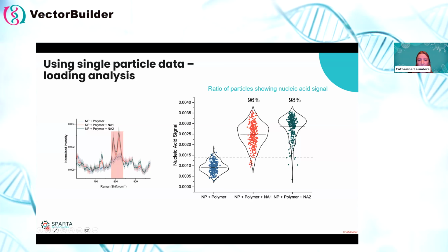So I should say this was a very short type of RNA that was used here. So we're expecting there to be tens to hundreds with a reasonable distribution of particles, rather than the more discrete, empty, full populations you might expect from the longer RNAs. So this is showing us the ratio of loaded to unloaded particles.